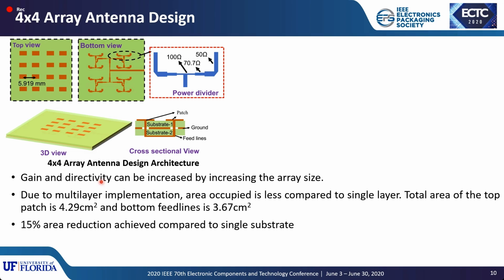Because of the implementation of this multi-layer architecture, the area occupied by this one is nearly 15% less compared to the single substrate layer. This is because as you have the feeding lines on a different substrate and the patches on a different substrate, the coupling effects are less, so that each patch can be placed close to one another.